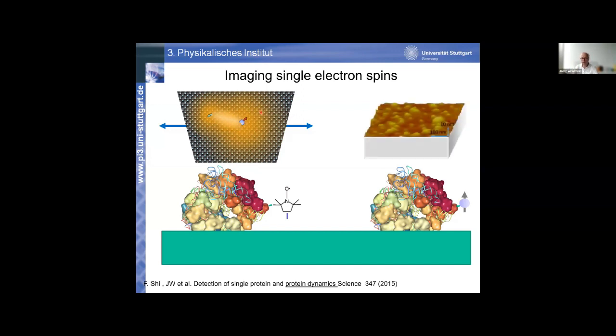And the result you see here: we were putting these proteins on the surface. They like to stick on the surface because they have Coulomb interaction. Then you scan across the surface with this structure here, and you see all of these blobs, and every blob marks the position where the magnetic field at the surface is particularly large.